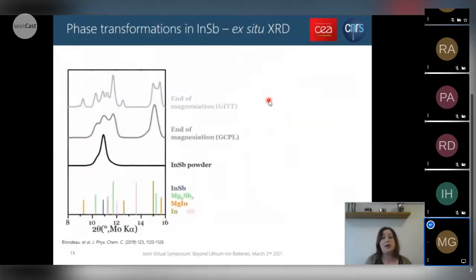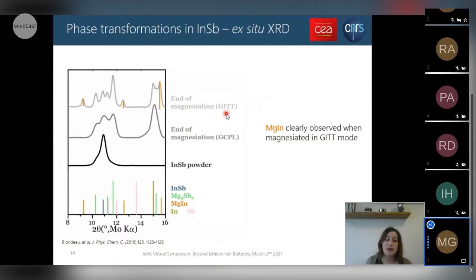To go further in the understanding of this crystallization and amorphization of the MgIn phase, we compared an electrode that we magnesiated, as seen before, in the classical galvanostatic cycling. Here you can see no MgIn in this case. And we compared it with an electrode that was magnesiated in GITT mode, where the electrode has time to reach a steady state and magnesium diffusion has time to happen. In this case, after the GITT measurements, we can clearly see that the MgIn phase is well crystallized, it's really occurring.